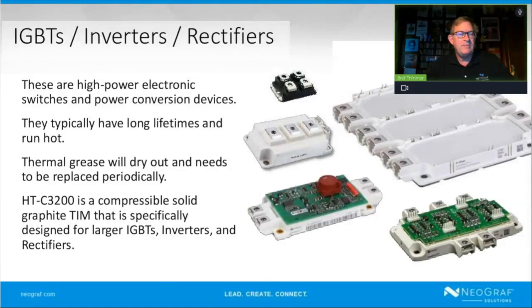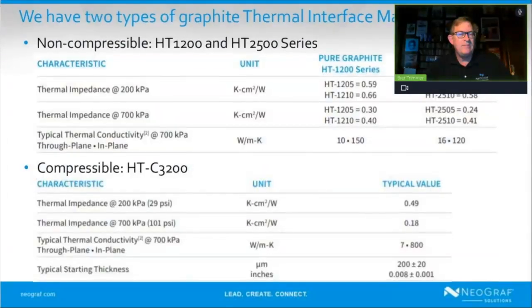And we'll talk about that a little more. Excerpts from our data sheet, these are available on the neograf.com website. We have two series of HiTherm, the 1200 series that is non-compressible, and by non-compressible, it compresses about 4% at 700 kilopascals. So it'll compress a little bit, but it won't compress a lot. And then we have the compressible material, starts off at 200 microns, and then compresses down. It can go down to about 30 microns, depending on the pressure you put on it.